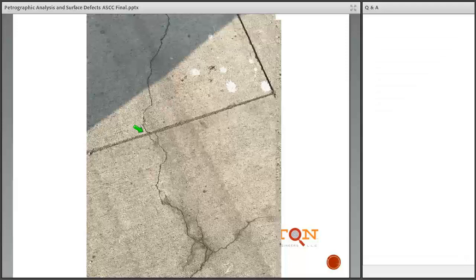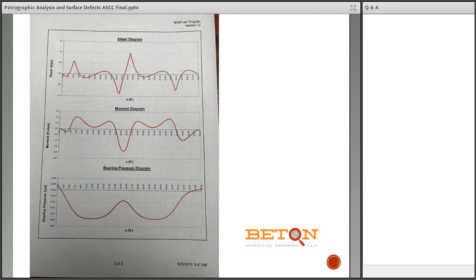But if we go further into the analysis and take a look and see what's happening, we find that an engineering analysis, just bending moments and bearing pressures and analyzing the slab as a beam on an elastic foundation, shows that in actual fact the pavement is inadequate. And it cracked early on because it was driven on at an age of about 12 days. And as a consequence, it's not capable of withstanding the garbage truck loads that it's seeing at an age of 28, or for that matter of any age, based on the strength that was available.